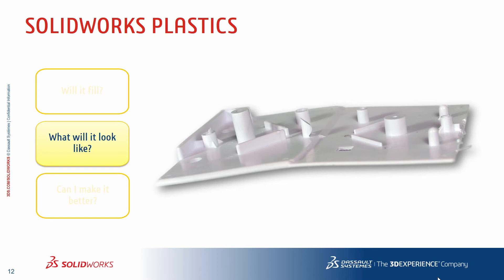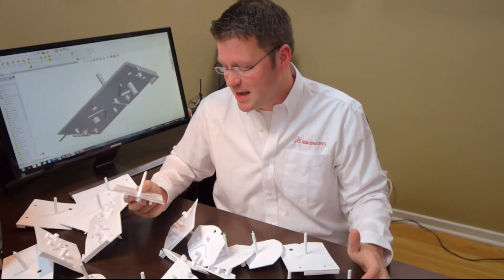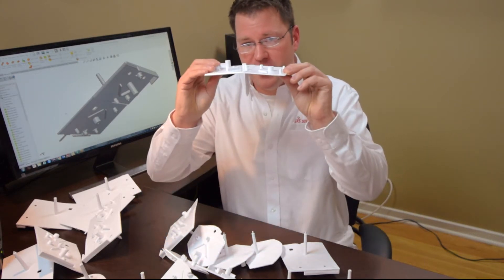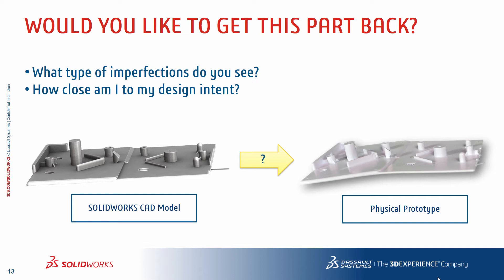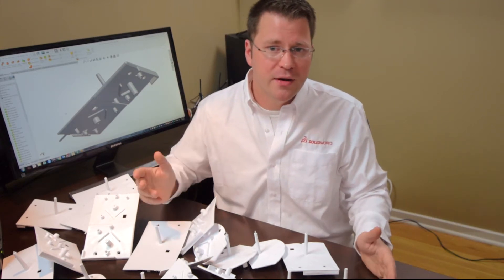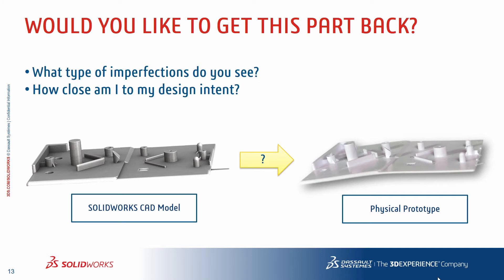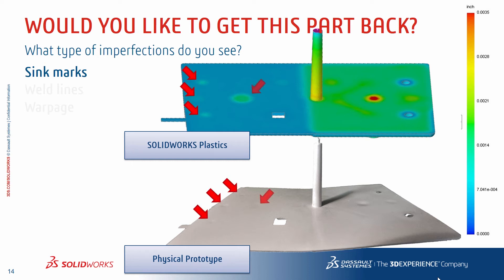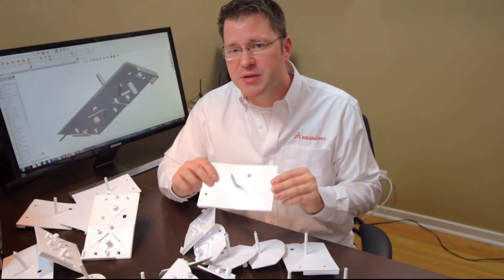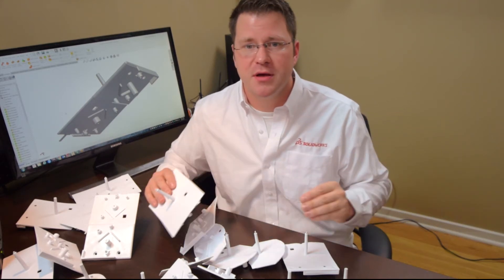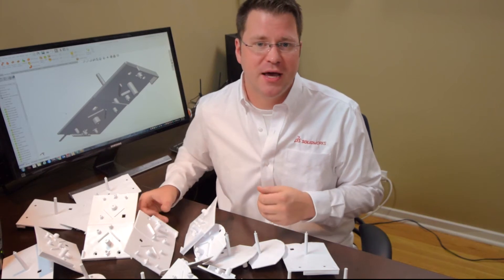Base-level information like this helps me understand how hard and expensive this part is going to be to fill. We can see the part can fill just fine and it's going to be safe in my machine. But what's this part going to look like once it's ejected from the mold? We can see on our physical examples here there's actually a lot of defects. There's a warping out of plane that we call potato chipping. On the left-hand side I have my CAD model — the idealized geometry I envisioned. On the right-hand side is our physical prototype. The first defect that really stands out are the sink marks — just a few thousandths of an inch, but with my well-polished, shiny mold surface, I can easily see them on the top. SOLIDWORKS Plastics predicted these exact same sink marks in magnitude and location, so right away I can understand that this part is not going to come back very pretty.